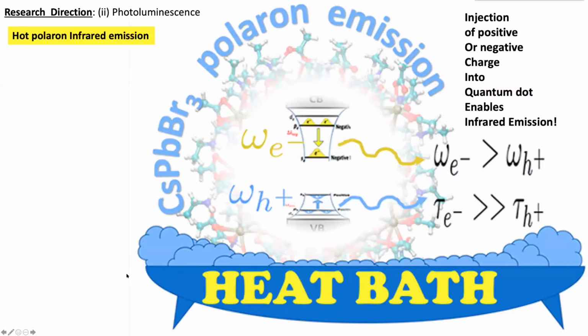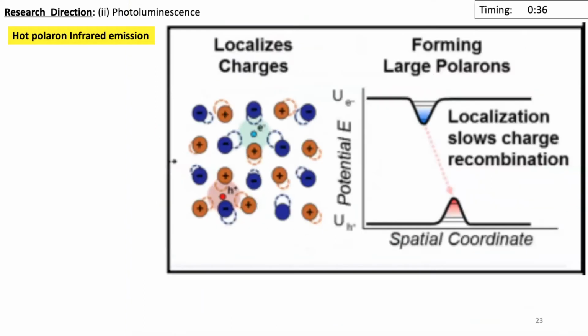If instead of photoexciting, one injects a charge and then just excites it by infrared, those quantum dots can serve as emitters in the infrared range, which is a challenge because the infrared excitation is very close to frequencies of normal modes, and energy dissipates quite quick.